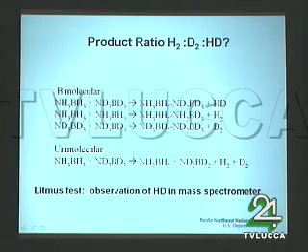So what we did was we can make this, or you can buy this from Aldrich, and we can deuterate the material or make deuterated material. And so the concept is to make a homogeneous solid mixture of a per-protiated and a per-deuterated species. If it goes by a bimolecular reaction, we should see all these different isotopes, HD, H2, and D2, depending on how well it's mixed, kinetic isotope effects. If it's a unimolecular reaction, we should never see the mixed isotope. It should just eliminate H2, D2, and then polymerize and give you the polymeric species.